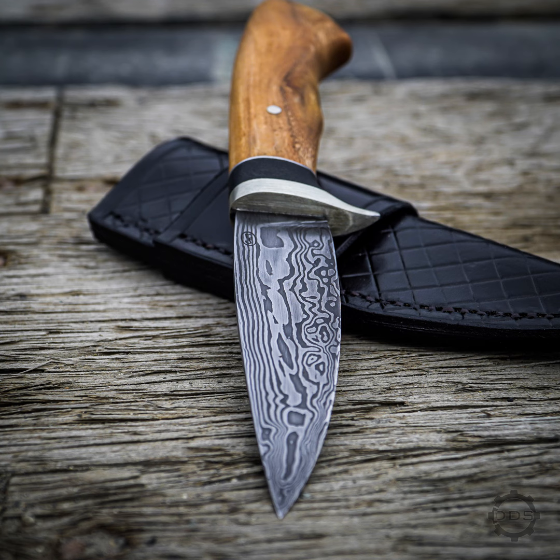So I start with very clean steel. I adjust the atmosphere of the forge to where it doesn't really produce any scale, and then I forge weld at a relatively low temperature. So basically I take that first stack, and it's 16 layers. There's 8 of the nickel steel and 8 of the non-nickel steel alternately stacked. And then I weld the ends and the sides with a welder to hold the stack together, put a handle on it, stick it in the forge.